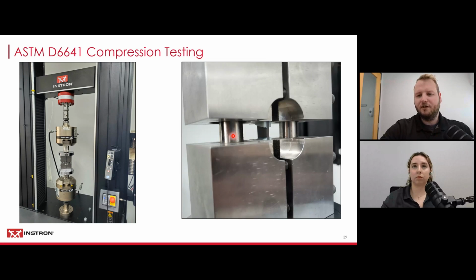Now, this particular fixture for the testing I used here was sourced from the company Wyoming Test Fixtures, which you can see here on the photo. And the specimen is installed in the fixture here. You can see this testing method is running with an unsupported gauge section, as opposed, for example, to the D695 testing standard. It's only a 13 millimeter long gauge section here between the fixtures, so it is really not possible to install any common extensometers between there to measure the strain.